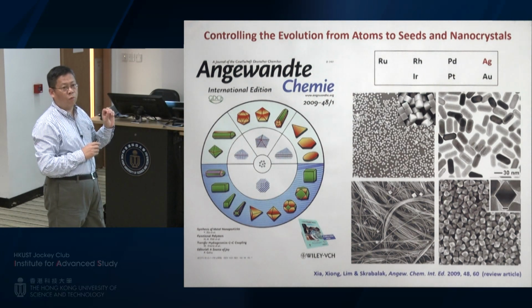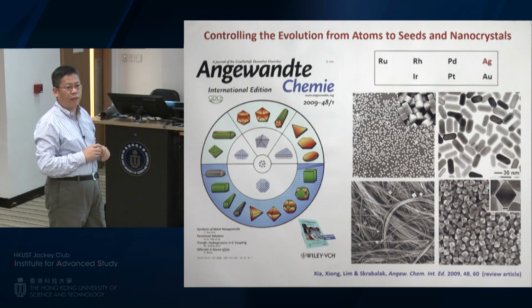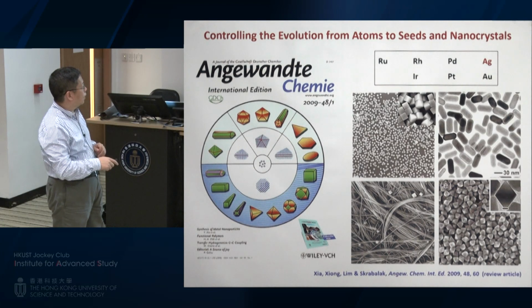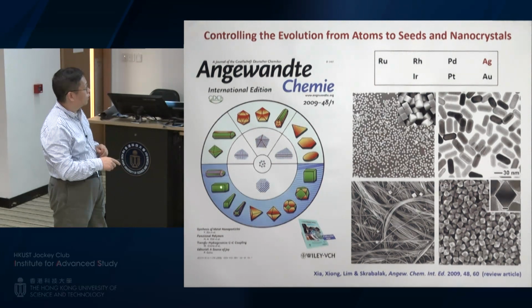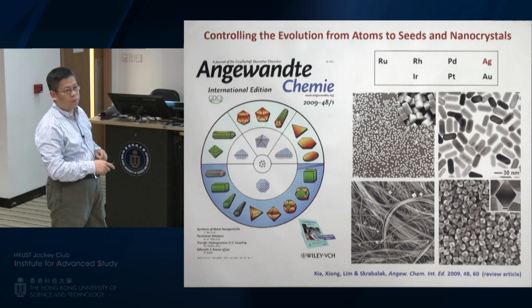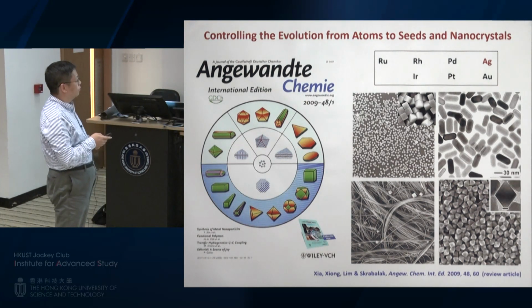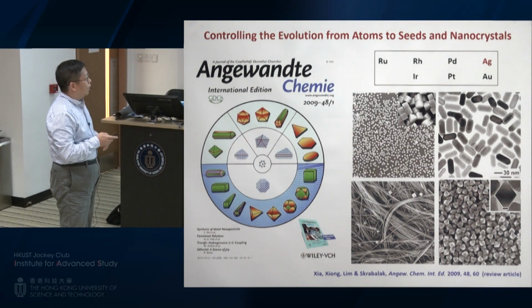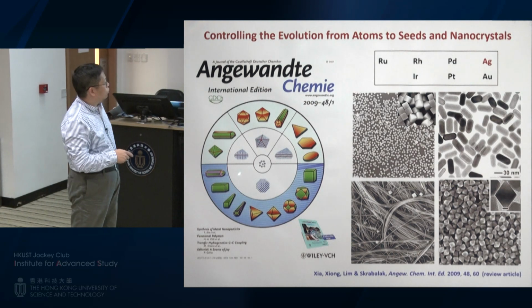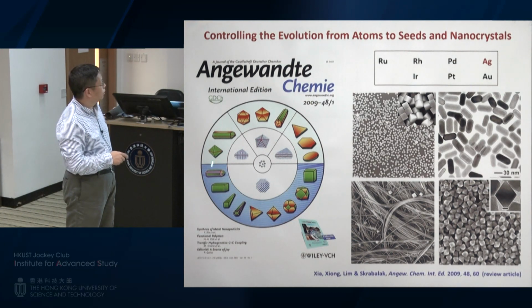It's bound by {100} facets. They can be formed under capping of same capping agent. However, if the kinetics is not right, they may be elongated along one direction to form this bar-shaped nanocrystals instead of this perfect cubes. So you can see the kinetics is also very important. Anyhow, by controlling the nucleation and the growth, eventually you can make just pure samples like cubes.